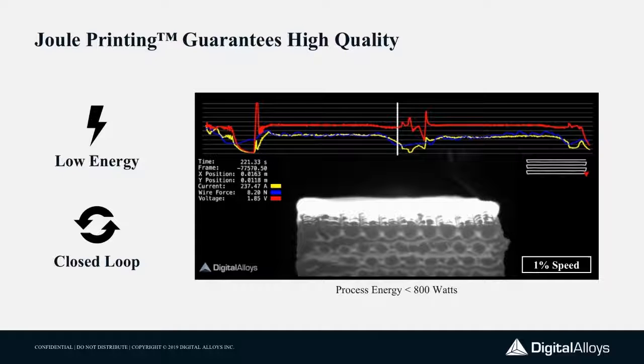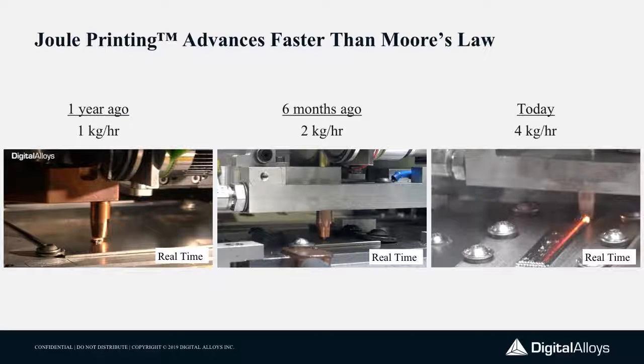So here's showing over the last year, let me try and cue this up again. Over the last year, you can see the advancement in speed that we've been able to achieve here, from about 1 kilogram an hour to about 4 kilograms an hour in titanium. And we've designed these first systems to actually go quite a bit faster than this even. It will depend on the part geometry, the true deposition rate that we can achieve. But this process doesn't have any sort of physical fundamental time constants, the way that a lot of other metal printing processes do, where you're waiting to move heat to the right place.